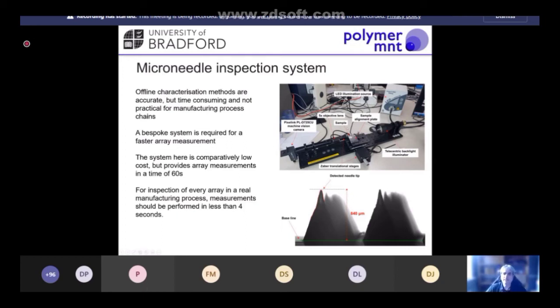It probably takes a minute running at its fastest speed to take a full scan. So it's still not fast enough to keep up with the full manufacturing process, but it does allow us to monitor the quality of needles during a production batch. We're just currently working on making a faster version of this, but we're still not going to get down to the requirements of making a measurement in less than 4 seconds to keep up with the process.